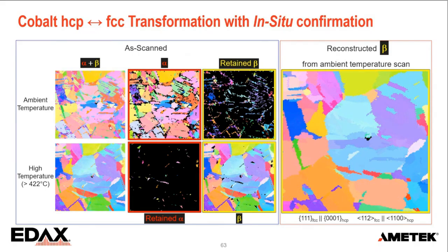And this image here on the right is actually the calculated high temperature structure based on this ambient temperature measured structure. So when you compare the reconstructed one with the measured high temperature one, you see how very close that is, including most of the twinning and all the low angle boundaries we have in here are actually still preserved and reconstructed successfully from the low temperature structure. So that gives a lot of confidence in what we can do.